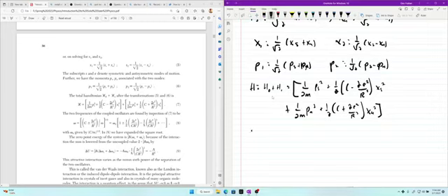Okay, the summations in equation 11 have been evaluated, and for FCC, the sum over j of P_ij to the negative 12 is 12.13188, and for P_ij to the negative 6, it is 14.45392. I guess they did it for a unit cell, is my understanding. There are 12 nearest neighbor sites in the FCC structure, and we see that the series are rapidly converging and have values not far from 12.